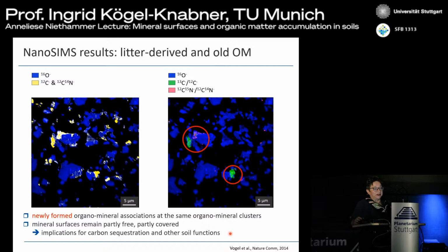And this has implications for carbon sequestration in soils, but also for other soil functions, because this means we have these small spots where we find this new carbon, and we have these spots where we have generally carbon in the soil, but a lot of the surfaces are available, and at these surfaces, other things can happen. These surfaces can produce cation exchange. If they are iron oxides, they can participate in redox reactions. In general, these surfaces can also participate in weathering.